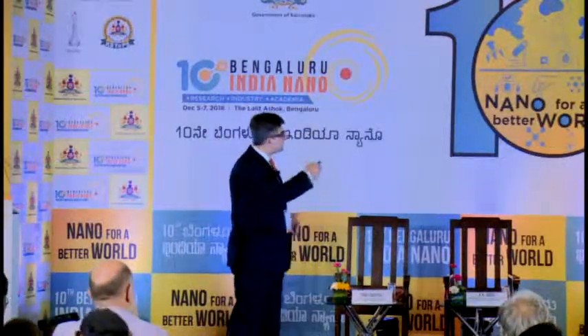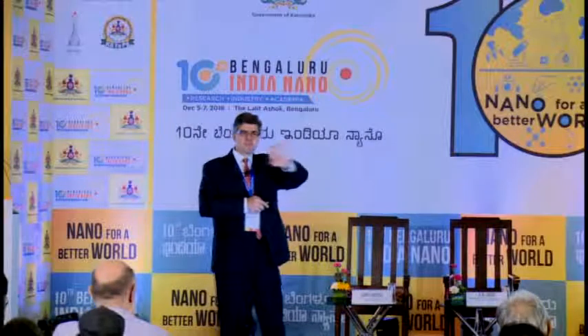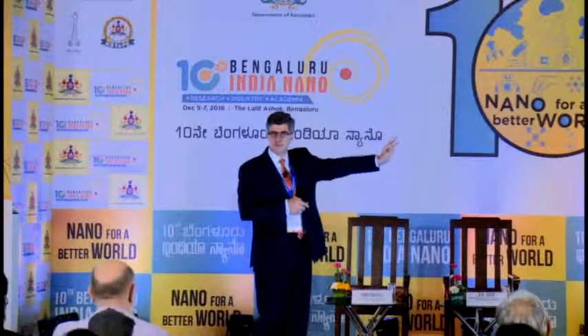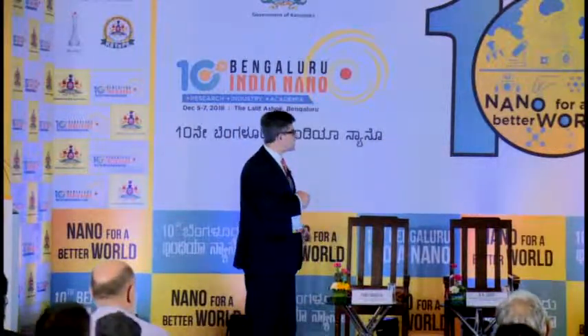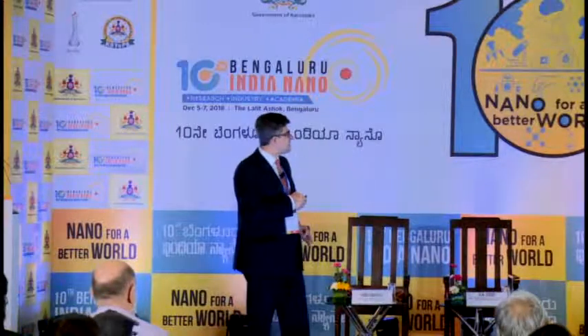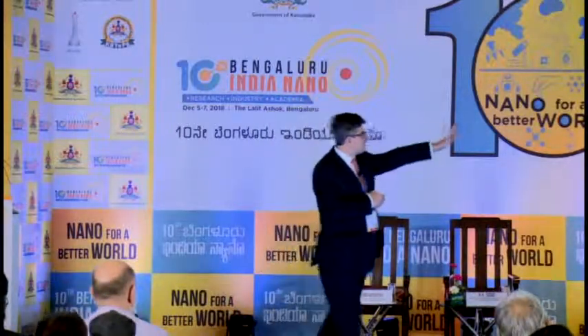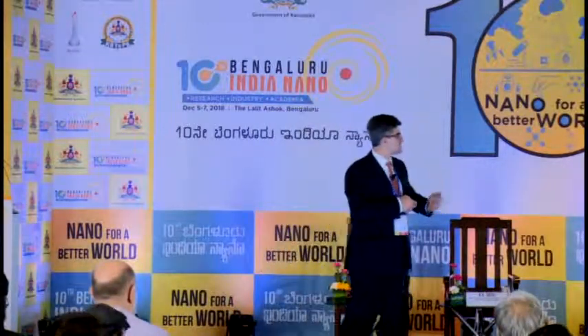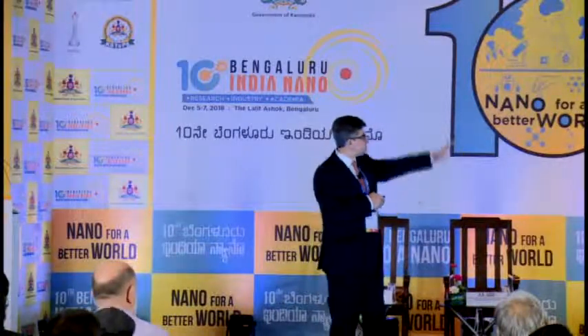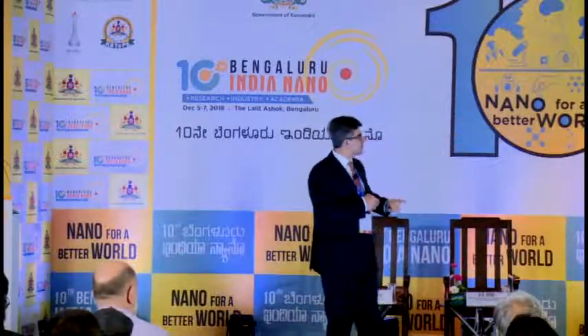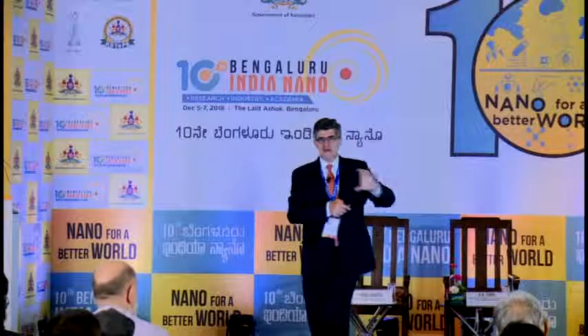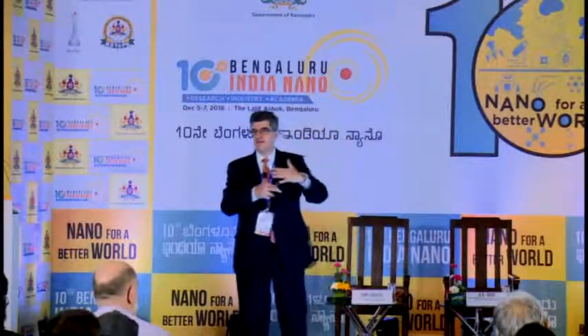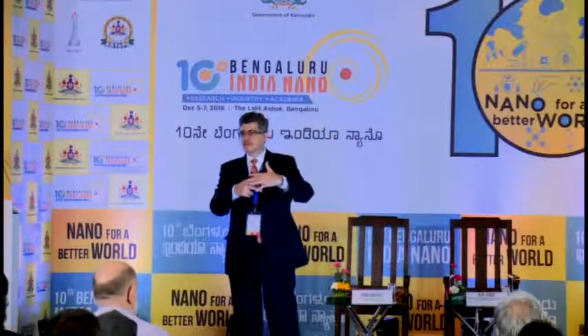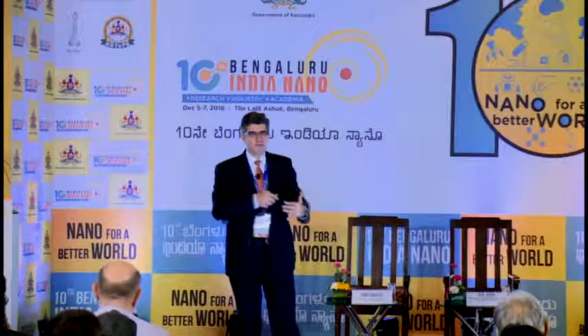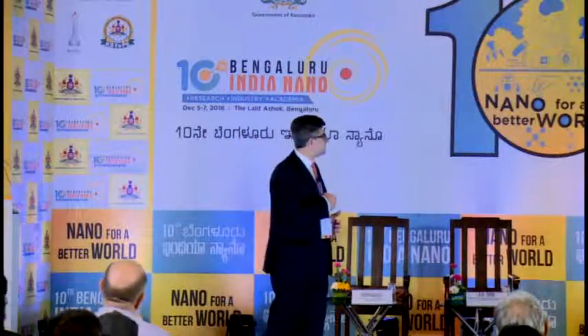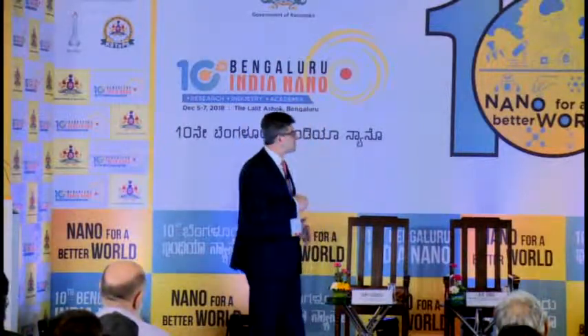What we do, we take this ceramic material that has monolayers of atoms like aluminum or silicon. We etch this layer of atoms away. And if you look at the high resolution STEM images on the right side, you will see that layers, dark layers of atoms disappeared, and there is now space between the layers. After etching, we got a weakly hydrogen bonded structure, which can be delaminated into single sheets.